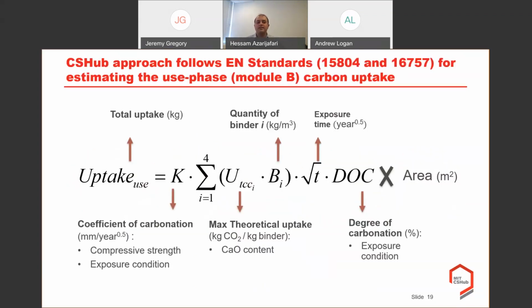So far, there is a standardized method in European standards 15804 and 16757 for estimating the use phase, module B, of the carbon uptake. And again, it follows the Fick's diffusion law. You have the coefficient of carbonation here to estimate the uptake during the use phase in terms of kilogram CO2, let's say. And this coefficient of carbonation is a function of the compressive strength and exposure condition in these standards, meaning that there are some predefined values for different compressive strength ranges and the exposure conditions of the concrete elements that will help us fill in and use the appropriate values for K, the coefficient of carbonation.